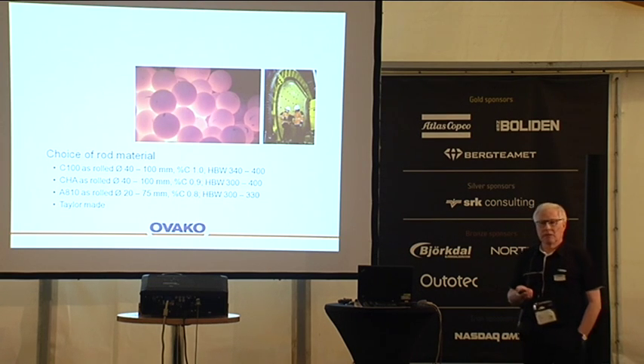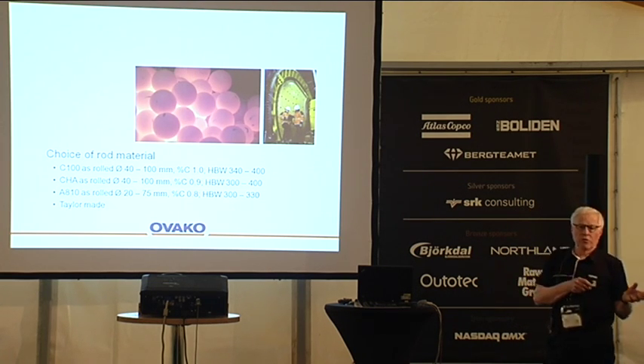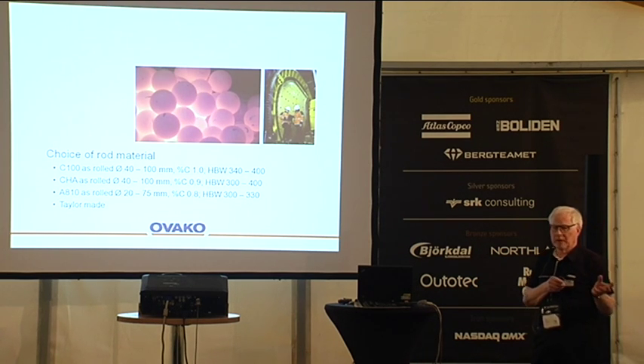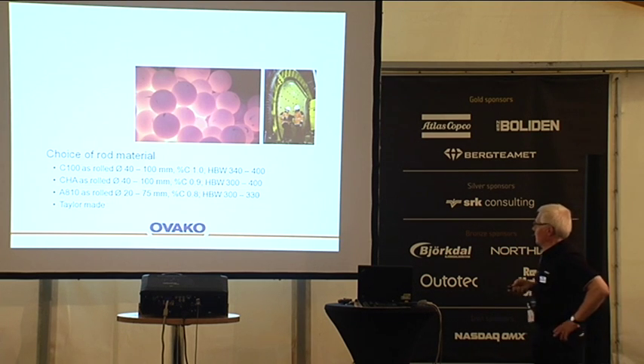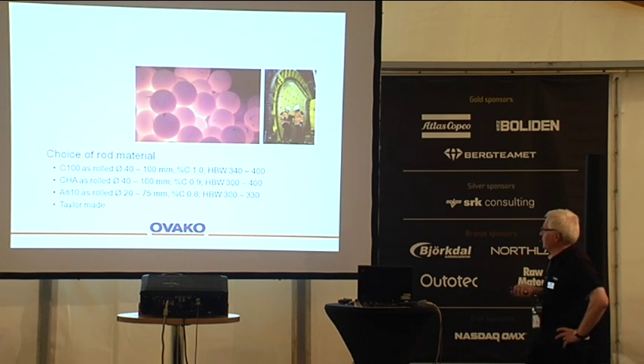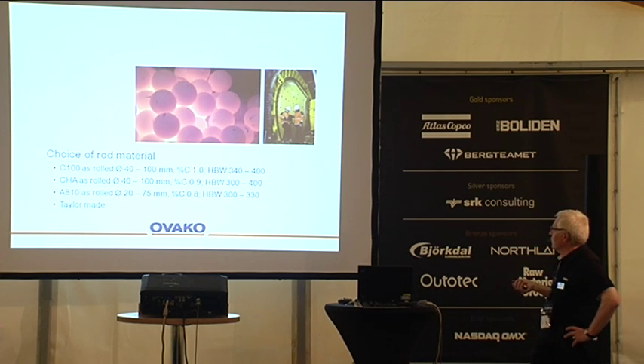Choice of material, that means selecting steel, is a very important part of the process in order to optimize the conditions in the grinding. We have today a number of standard grades that we are using on rods. There are around 1% in carbon. The next level, which is slightly softer, is 0.9. And then we have another at 0.8. So we can see differences depending on what kind of minerals you are grinding. But we can also, as a steel producer, offer a tailor-made solution.